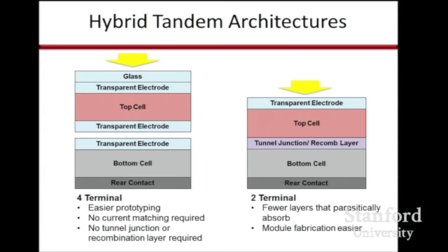We're considering both a 4-terminal architecture where we basically have 2 different solar cells, and the top one is transparent so that the low energy photons can go right through. In the short term, this is easier for us to make, but in the long term, we'll probably build it all on one substrate and match the currents of the 2 cells. We'll do that to get rid of these transparent electrodes, which can absorb some of the light.